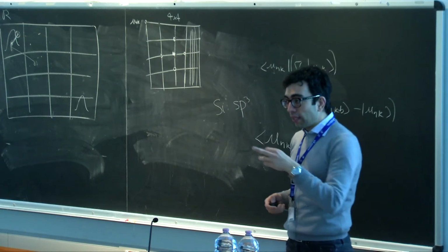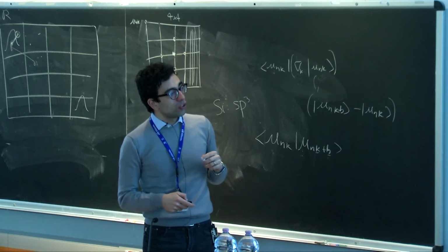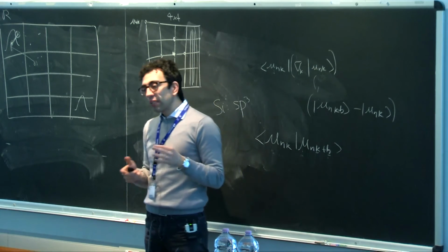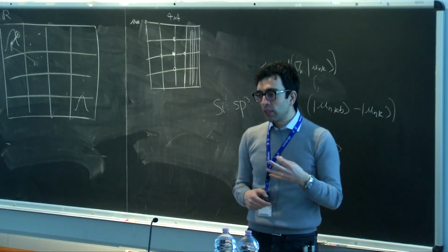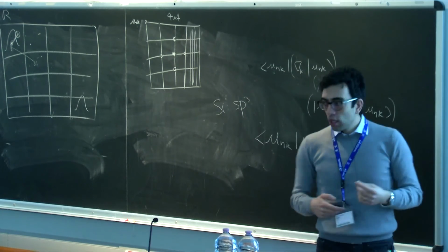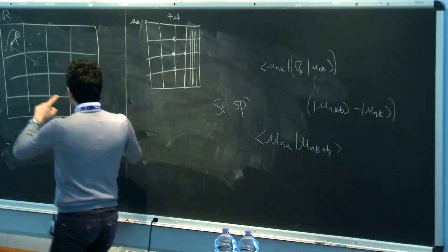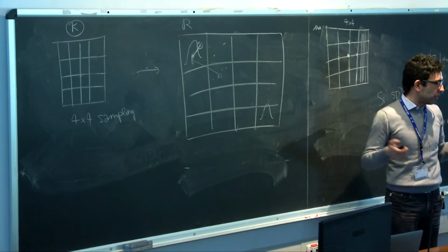We'll see later, after the coffee break, an example of silicon, which we'll do in the afternoon. Antimo and Valerio will show you that, for instance, in silicon, if you do just 4x4x4, you get an interpolation which is already reasonably good, but not perfect. If you go to 6x6x6, things improve a lot, because in that case it means that there is still some overlap between things which are at a distance of 4 unit cells.